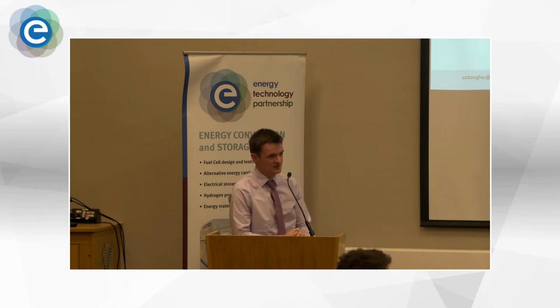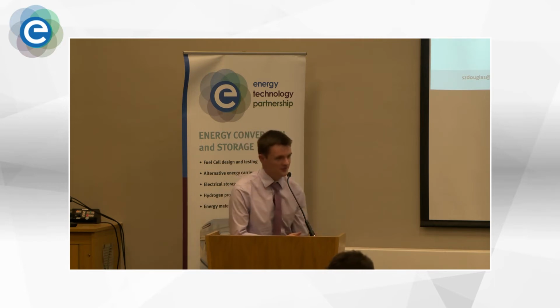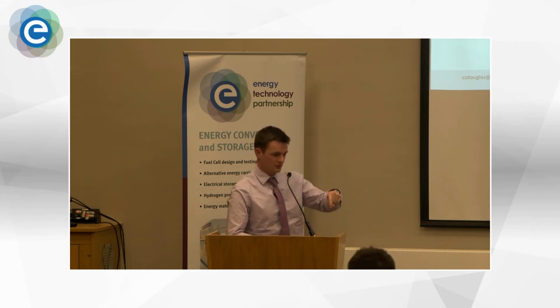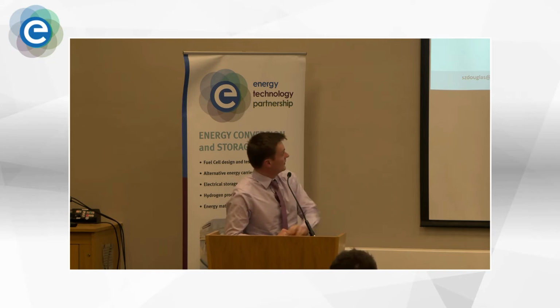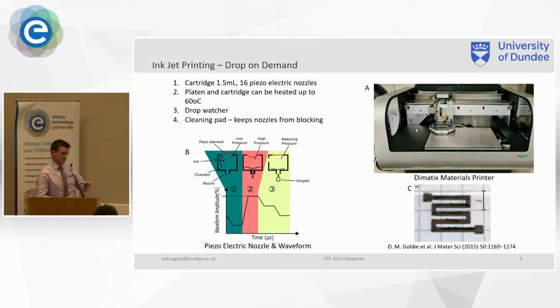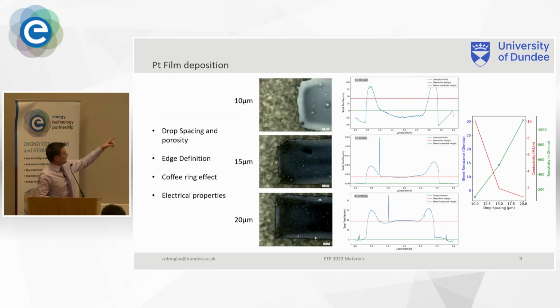What's the drop spacing, and what does that mean as a concept? You've mentioned drop spacing and porosity. What does that mean? Yeah, so the drop spacing is, in drop-on-demand printing, this process drops a single droplet, and it does that at a rate of 5 kilohertz. And then we define the drop spacing, which is 20 micrometers. So it drops at a rate of 5 kilohertz, but the drop spacing is the distance between each droplet, of about 20 microns, as you said. Yeah. So they overlap on top of one another. Do you know the diameter of an individual droplet? About 45 micrometers, yeah.